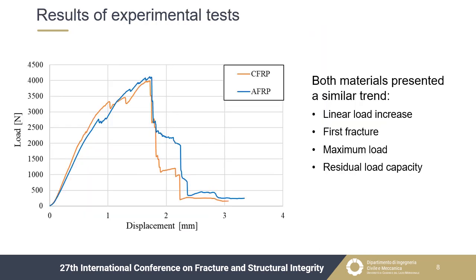The data obtained from the experimental test campaign are reported in this graph, in terms of load versus displacement. In particular, a single curve was plotted for each type of specimen, that was representative of the results relevant for the 5 specimens tested for each type. For both CFRP and AFRP, a maximum load of about 4000 Newton was recorded, even if that of the latter was slightly higher. The maximum displacement at break was the same for both types of specimens, and it was equal to 1.8 mm.